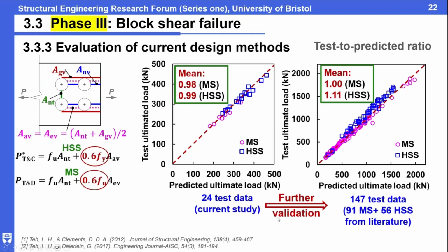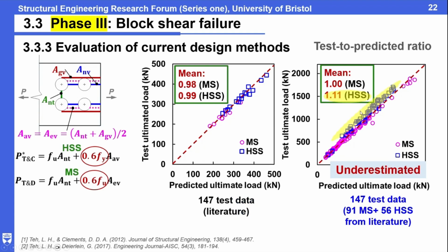So we extracted the test data from literature, including mild steel and high strength steel. It's around 147. We did the comparison again. We found that for the mild steel, it's okay, and the average of the test to predict ratio is 1. So this seems okay. Mild steel considers fully developed strain hardening. And for the high strength steel, you will find that it is a little bit above. It means the high strength steel is underestimated just by using the 0.6 Fy. So maybe there are some reasons we can look at further.